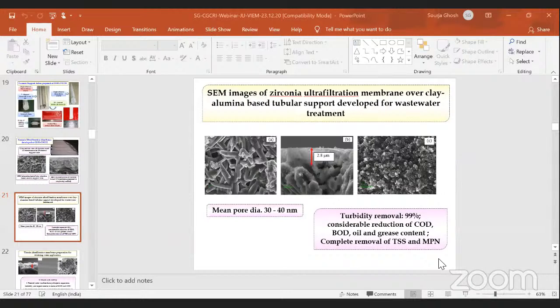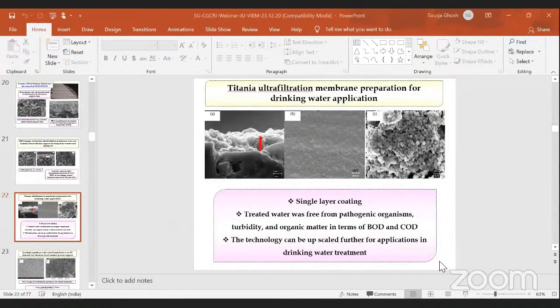This is another microfiltration ultrafiltration membrane, zirconia over clay and alumina support tube. This membrane showed a pore size of 30 to 40 nanometer, and when applied for treatment of wastewater, it resulted in turbidity removal of 99%. Then considerable reduction of COD, BOD, oil and grease was achieved with complete removal of total suspended solids and MPN, that is the most probable number representing the microorganism concentration in the water.